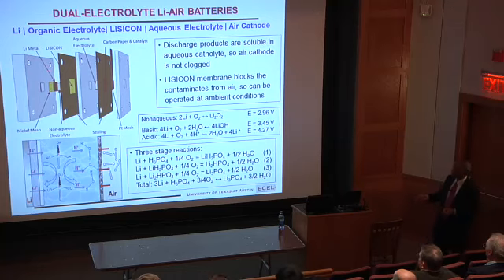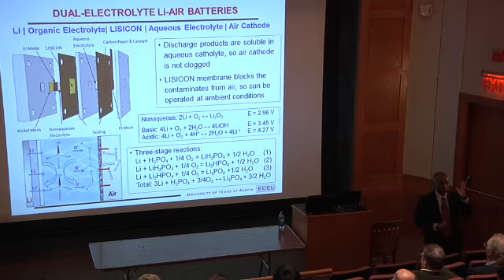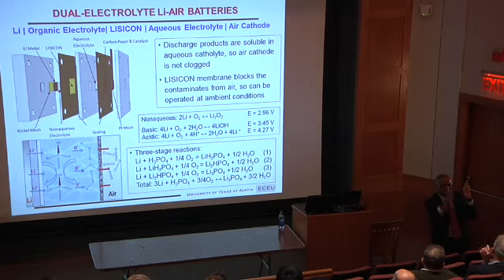So what we are doing, we are trying to do a dual electrolyte system. That means we have a ceramic separator. One side non-aqueous electrolyte with lithium. This side aqueous electrolyte with oxygen. So I do not have to worry about contamination from air because it's aqueous. I do not have to worry about clogging because it will form lithium hydroxide, soluble. But there is one huge challenge. My separator here, the ceramic membrane, should allow only the lithium or sodium to go through. It should not allow my proton to go through. It has to be selective. And that is a solid state chemistry and physics problem.